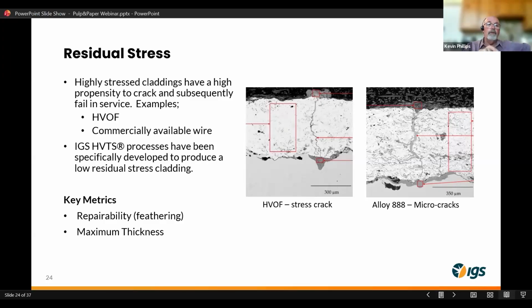When you consider residual stresses, the nice thing about having low residual stresses is that the cladding is repairable in that it can be feathered. If there has been some deterioration of the cladding itself, I'm referring to the HVTS, it can be repaired, giving it a very lengthy lifespan of 10 plus years before replacement is actually required.